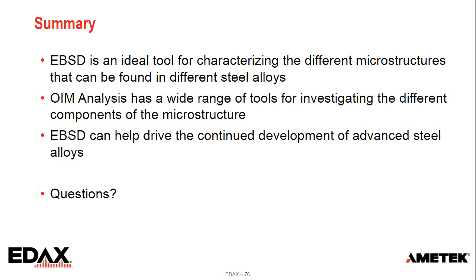And here's a question: without EDS, will EBSD indexing be correct? That all just depends on the phases you're looking at. For example, if I'm looking at just FCC and BCC, a ferritic austenitic steel, EBSD does great with that, or some of the carbides, or the sigma phase, which is different. It will differentiate those, no problem. It's when the crystallography starts to be really similar that EDS is helpful. And then when they're similar both chemically and crystallographically, that's martensite, they're both similar in both regards, then we have to use a third approach to try to differentiate those.